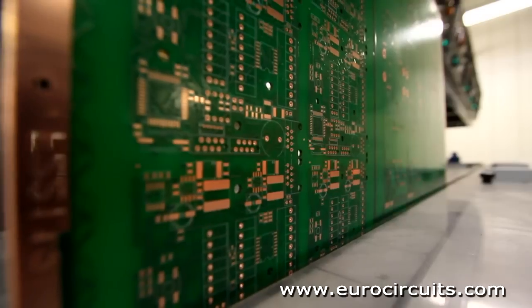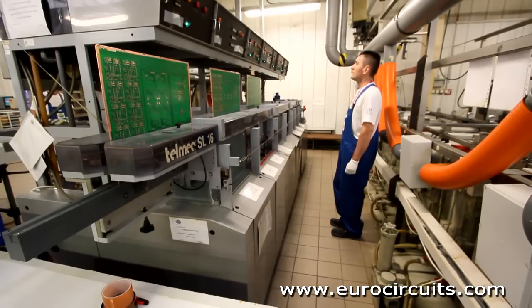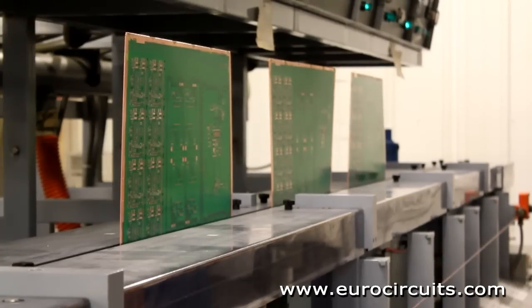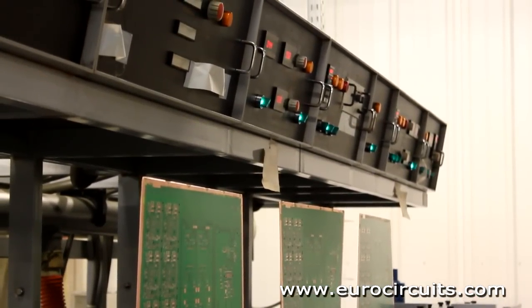The electroplated gold is needed for edge connectors which will require repeated insertion and removal. Electroless gold gives good solderability but is too soft to withstand repeated abrasion.